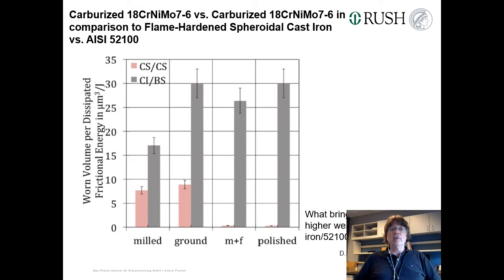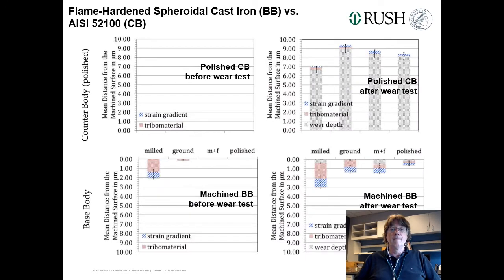We did the same thing with flame-hardened spheroidal cast iron, and that has been tested against the bearing steel 52-100. And you see, this is the red ones. This is what we did with the carburized steels. And this is what we did with the cast iron against the bearing steel. And you see the wear was much, much larger. And if you again check the same picture, all the wear has been brought about by the 52-100 steel, even though this was much harder than the cast iron.